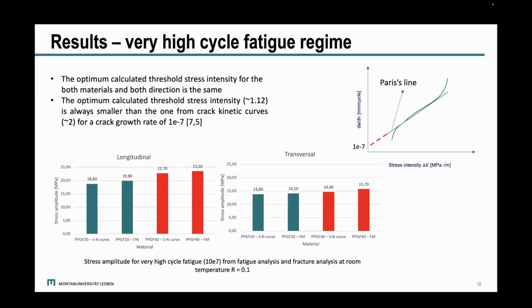Then we have a look at the results. At first for very high cycle fatigue, you can see the stress amplitude for 10 million cycles from the calculations and from the measurements. The difference between the data is in all of the cases less than 10%. Also, I would say the data are acceptable. And the interesting point is that for all the materials and for all the directions, for both polypropylene with 20 and 48% glass fiber, and in longitudinal and transversal direction, the optimized threshold stress intensity is always 1.12, which is smaller than the measured one. But we know that with our instruments, we are not able to measure the threshold stress intensity.